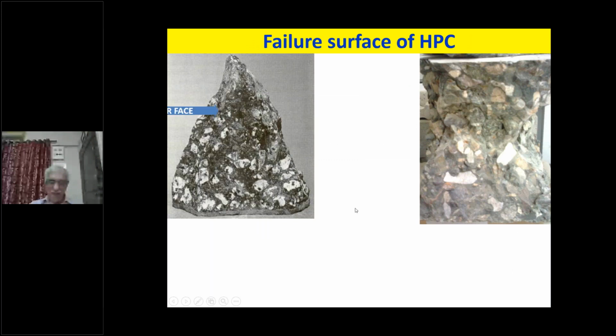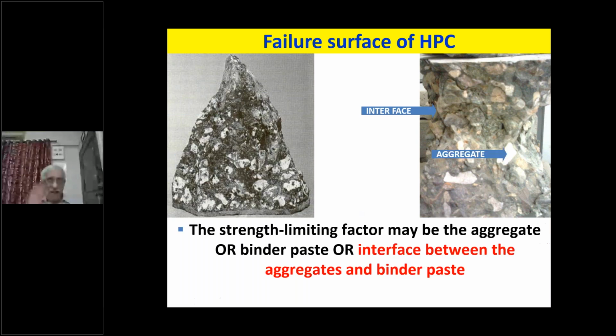So interface has to be strengthened, and if the aggregates are also failing, then aggregates have to become stronger or get a better source to give you higher strength aggregates. But generally, the interface, if it is strengthened, you can exceed 60 to 80 to 100 megapascal strength.